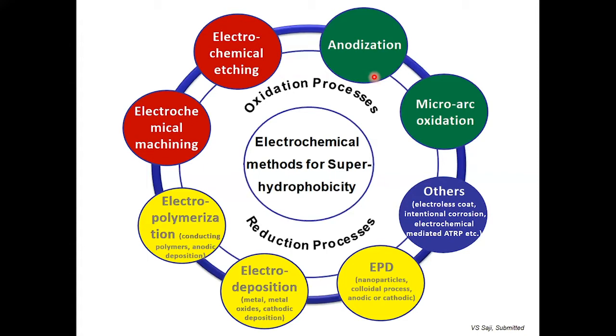The yellow highlights are the electrodeposition approaches. Electrodeposition is typically a reduction process. If you see the electrodeposition of metal or metal oxides, that is cathodic deposition. Electropolymerization of conducting polymers is usually an anodic process, anodic deposition. And there is an approach called electrophoretic deposition, which depends on the colloidal process, and it's a deposition of charged nanoparticles. It can be anodic or cathodic depending on the charge of the particle.